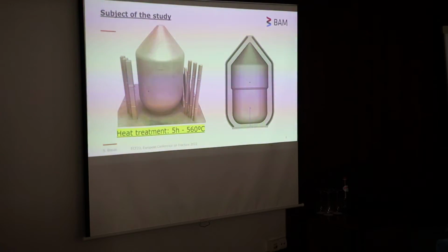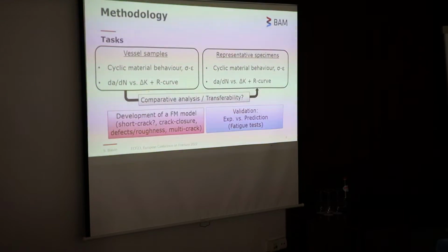So this is the archetype that we are using nowadays. It's a vessel of 316 steel, and the heat treatment was this one, 5 hours at 560 degrees, and you can see different areas in the component. 3 main areas: the cylindrical part, which can be divided in 2 because we have different thicknesses, and also the cone, which means that the building direction compared with the direction of the specimens is different in each place, and we want to check the performance in each position.